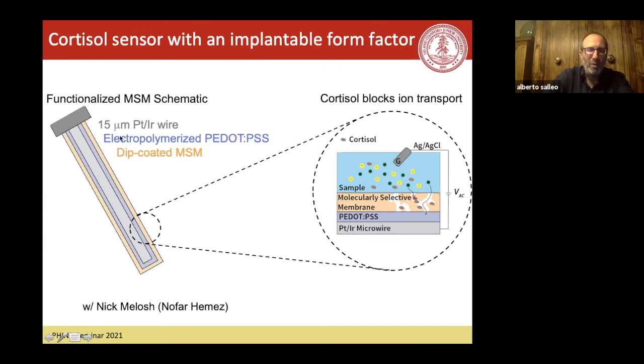So it's very handy. And then we helped them put together this molecularly selective membrane. So they dip coat into a PVC solution that also has the molecularly imprinted polymer. So if I look at a cross section here, I have my wire, the PEDOT:PSS, the selective membrane, and the PEDOT:PSS is needed because it reduces the capacitance, it reduces the impedance of the whole system. So it gives you a higher response system. And also the molecularly selective membrane adheres better to the PEDOT:PSS. And here's where your analyte sits.